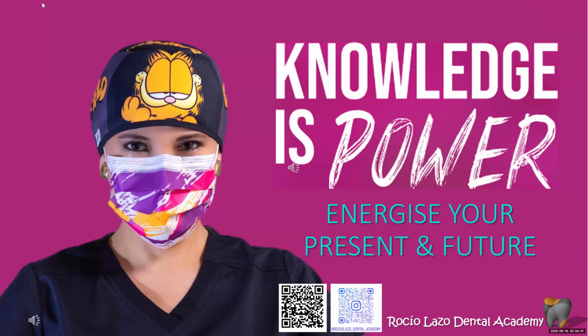Okay, perfect. A question here. Do you use caries detection dye? No. If you want to do regenerative selective caries removal, it's impossible to use it. Why? Because it's a chemical, and it will denature your collagen fibers. Remember, collagen fibers are so important for the interaction with the strontium ion, calcium, and phosphate ions, and to regenerate. So never forget.